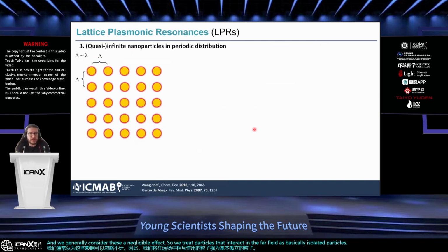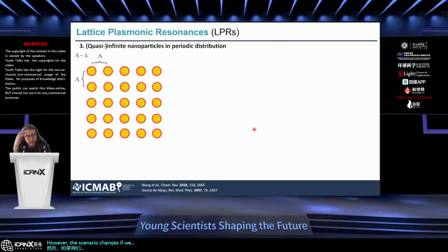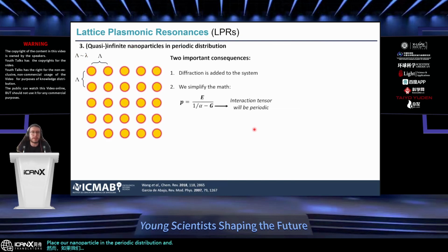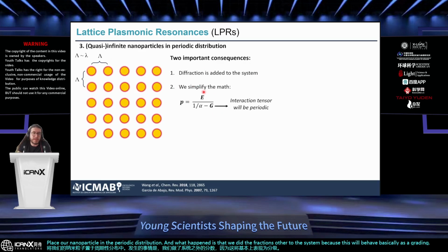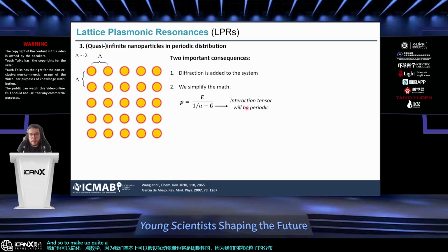However, the scenario changes if we place our nanoparticles in a periodic distribution. Diffraction is added to the system, because this will behave basically as a grating. We can also simplify the math a little bit, because we can assume that the perturbation tensor will also be periodic, since the distribution of our nanoparticles is periodic. And to make a long story short, you basically get down to this equation. What is important here is that in order to have a resonance, so basically in order to bring this denominator to zero, we create new conditions that are not localized plasmons.